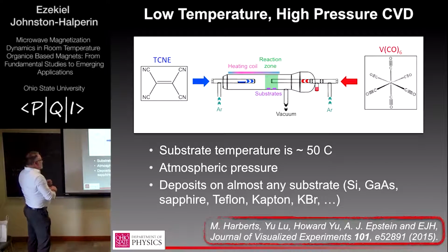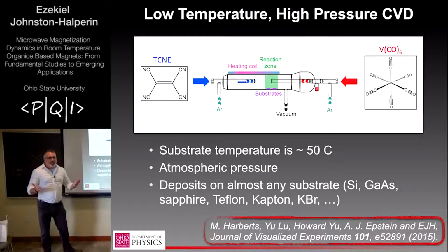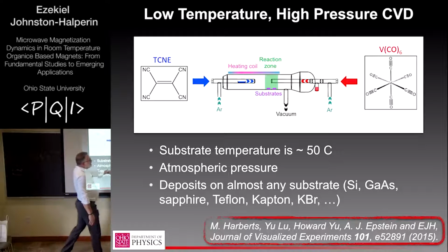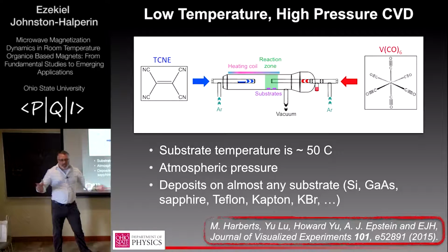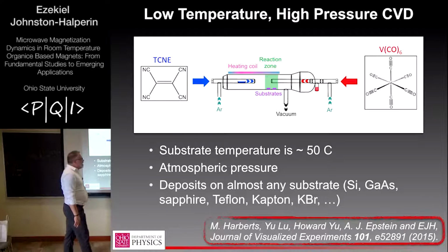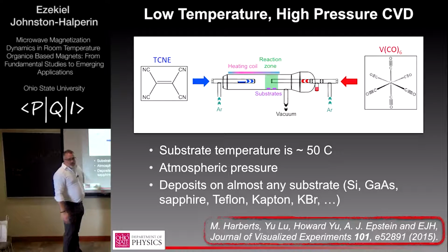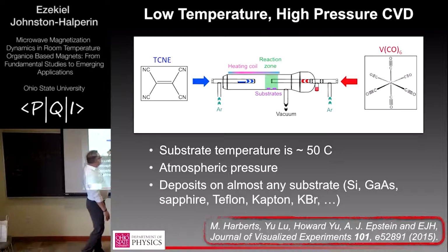So talking a little bit about how this material is grown, I said it was medium hard. The thing that makes it medium hard is this is not a commercially available reagent. So this VCO6 we have to synthesize ourselves. It's the kind of thing most chemists would be able to do, maybe with a little bit of practice to get it right. The TCNE is commercially available. But once we have those compounds, we basically just put them into the inlets of this reactor. We use argon vapor phase transport to bring the precursors into the reaction zone here, and set the substrate temperature independently from the precursor temperatures to control the stoichiometry and deposit.